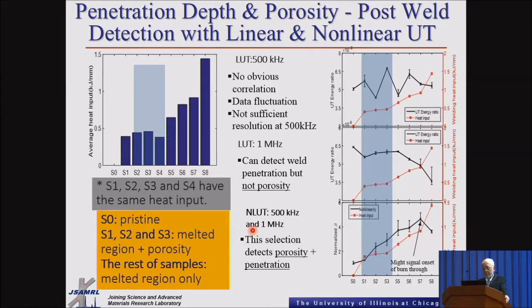Using nonlinear ultrasonics with 500 kilohertz, so that would be high harmonics, in between 500 kilohertz and 1 megahertz, what happens in this case, using the high harmonics, you use this beta parameter that was correlated with the heat input, and you can see that as you increase the heat input, you also have an increase in penetration. Now, remember that I mentioned before that in these two cases, it was very difficult to detect any type of porosity. In this case, it did. You can see they have the same heat input, however, you have some changes in the beta parameter, which indicated that porosity can also be detected using nonlinear ultrasonics.